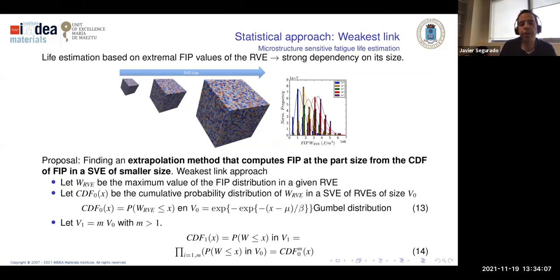And then we're going to obtain the value of each of those, in order to generate a probability distribution for all this set. Now, if instead of having this set of very small RVEs, we have bigger RVEs, then the probability of finding a critical grain is more probable in the bigger one, and depends on the ratio of volume. So what we can express here is the cumulative distribution function of failure, or of finding a critical grain, in a big volume V1, that is m times a smaller volume V0, is nothing but the power m of the original probability distribution.